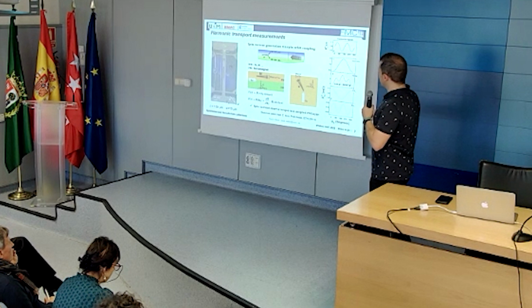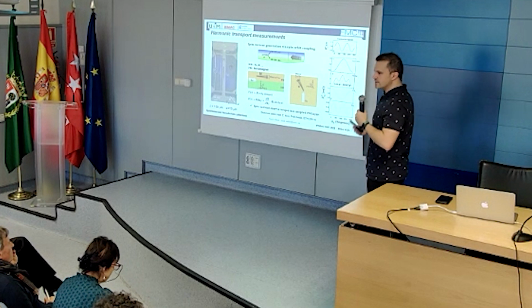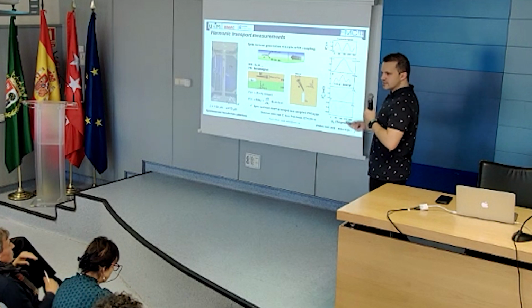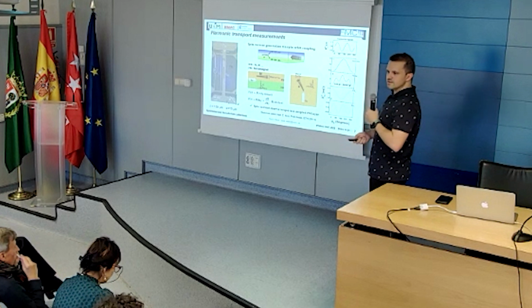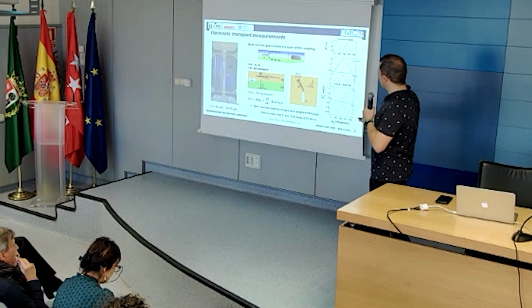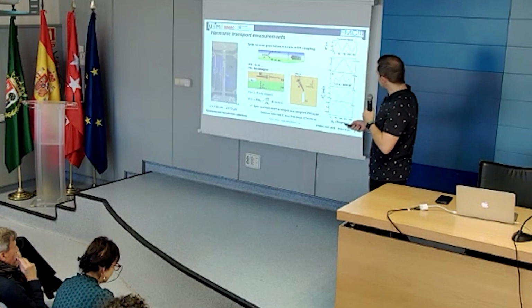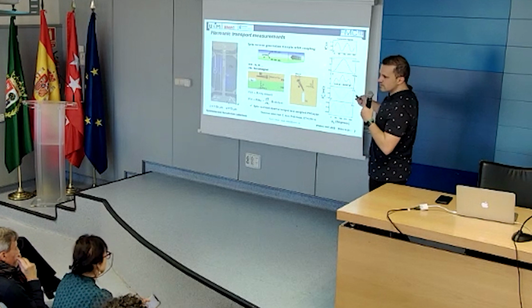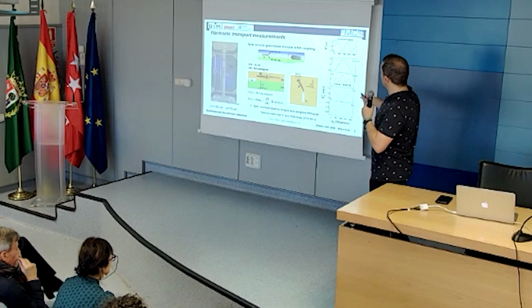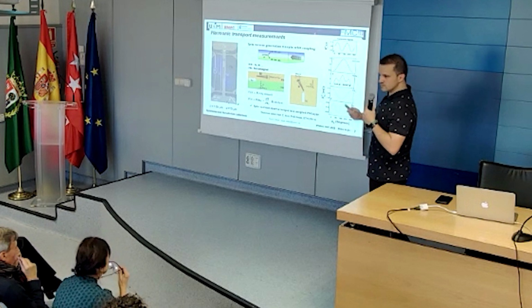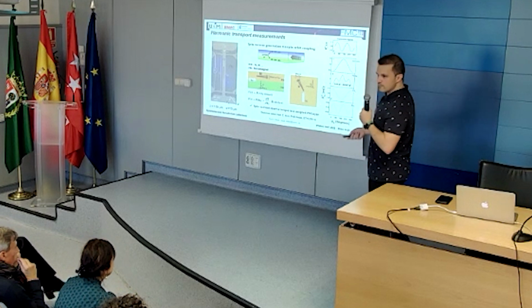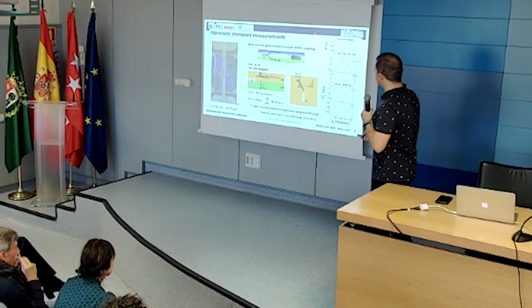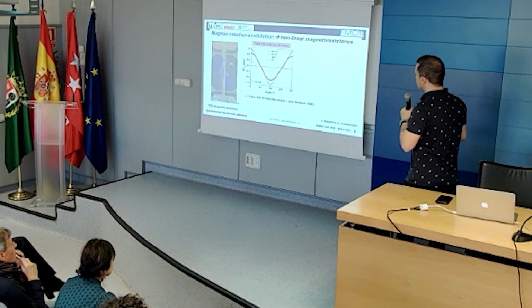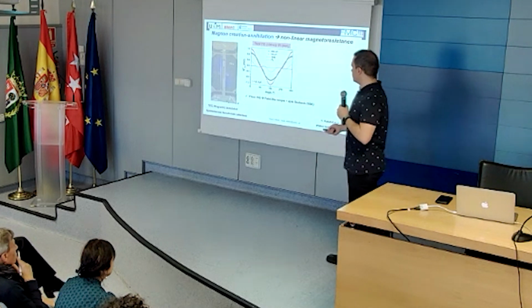The amplitude of this effect depends on the interface quality, how much spin you are generating, how much current you are applying, etc. On top of that, you will also have other effects like thermoelectric effects, and these also appear in the second harmonic. If you just stay with the first harmonic, what people typically do is this. If you do higher harmonics, you do this, and more things also. That's what I'm trying to show you today with Haripriya.